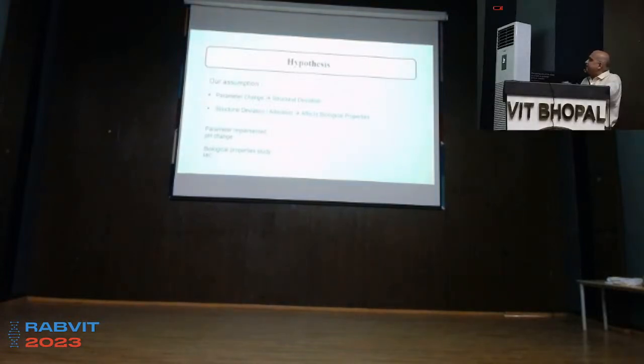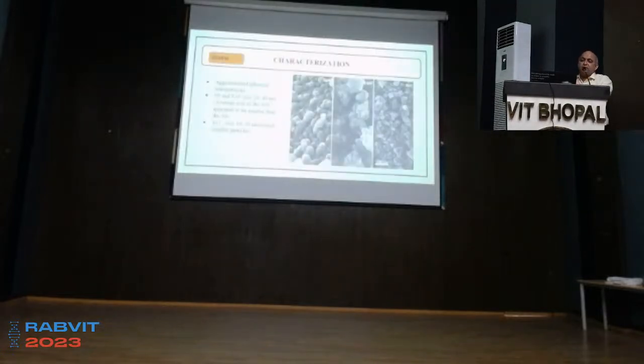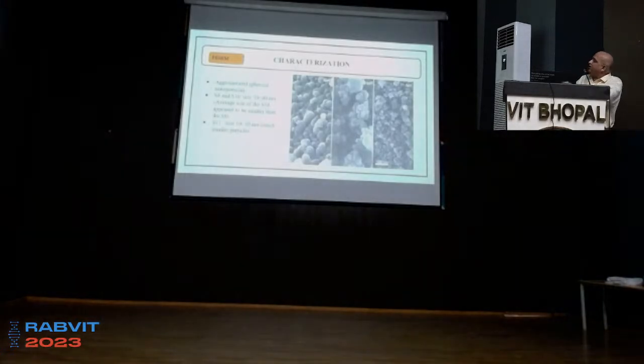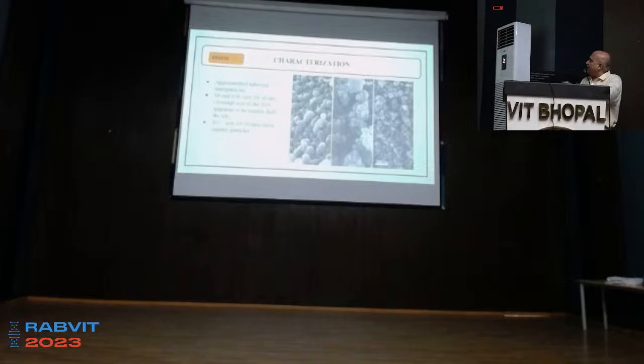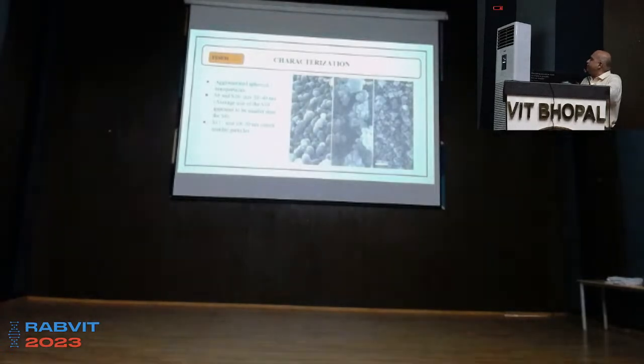So our hypothesis was we will change the parameter and see the structural deviation, and the structural deviation will give alterations in the biological properties. So this was our hypothesis. Now we prefer to make 3 different samples, one at pH 8 and the other one at 10, and then we targeted 12, but we could not achieve 12, so we constrained ourselves to 11.5.